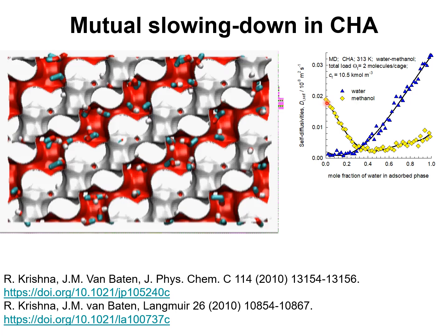We note here the data for self-diffusivities of methanol, indicated by the yellow diamonds, that the self-diffusivity of methanol is reduced due to increased proportion of water in the adsorbed phase. At the same time, the self-diffusivity of water is reduced due to increased proportion of methanol in the adsorbed phase.